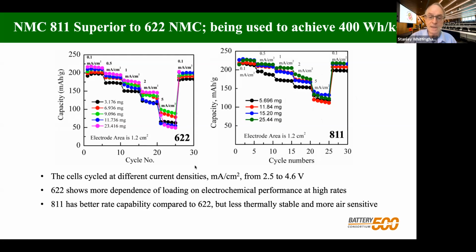But the challenge here, as I say, it's less thermally stable, but it's also much more reactive to the air. So this material has to be handled in a dry room or glove box. You can't handle it in a regular atmosphere. So it has to be, after being manufactured or prepared, it has to always be stored in an inert atmosphere. So with this material, we have in fact achieved 400 watt-hours per kilogram over about 100 cycles. And this was goal for this summer. So that was achieved.